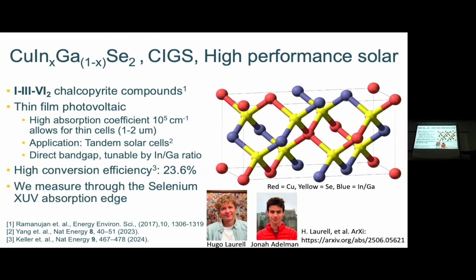So now let's press on just a little bit more. There's an interesting material called CIGS. It's copper, indium, gallium selenide, and it's a quaternary kind of metal dichalcogenide. And it has a very high solar efficiency conversion to electricity, around 24%. Doesn't really beat silicon. I mean, we're still going to put silicon on our house, but for some applications, this has been very important. And to get this high efficiency, it turns out you have to grow it deficient in copper. So you have to purposely introduce defects due to restricting the copper in the growth.